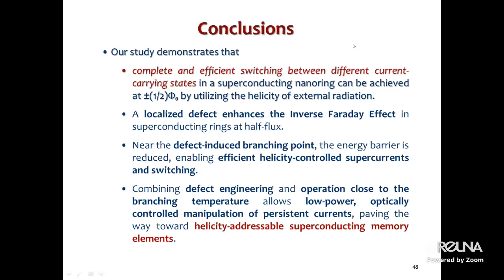But this picture is related, basically, to the critical temperature, how it behaves. And then if we already have two valleys and the barrier between them, then the system is somewhere on the top of this hill, on the top of this kink. With the external laser we can push the system either to one valley or to another valley, and then the barrier preserves the state from moving from one side to another, for example, due to fluctuation.